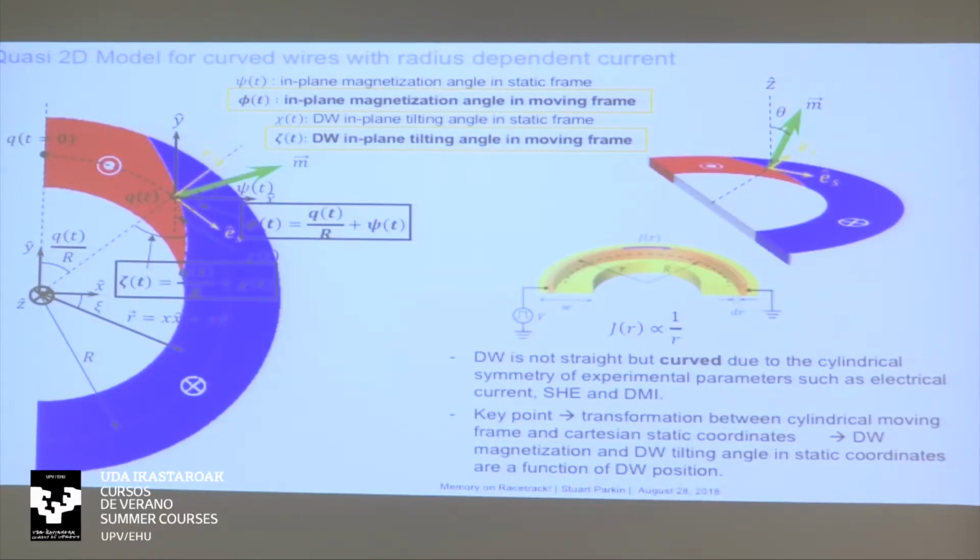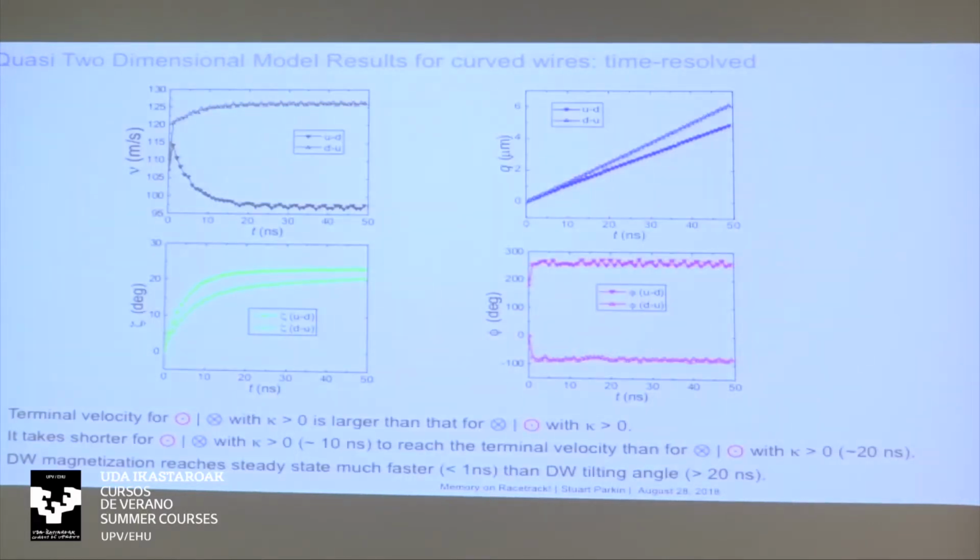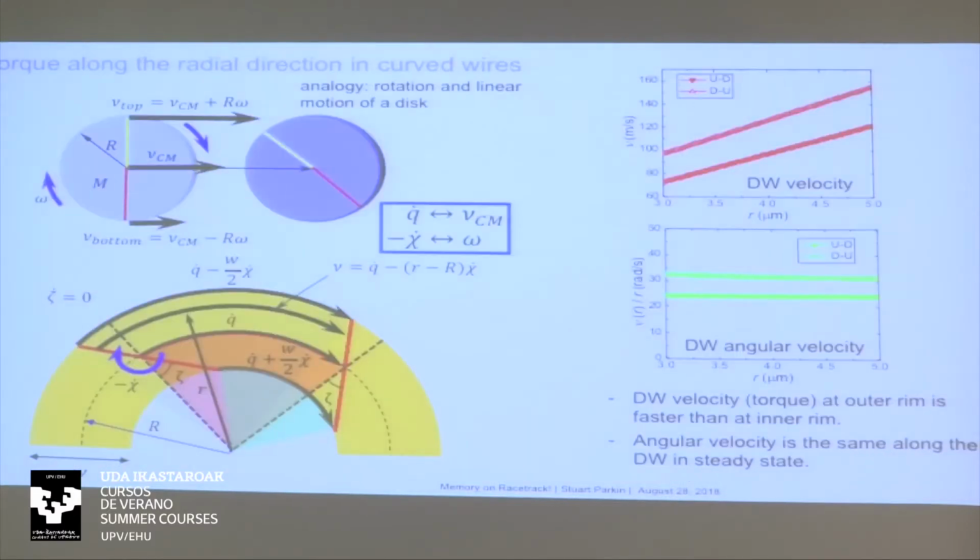We have to switch all that magnetization, and that turns out to take a very long time. So within the wall itself, the wall moments rotate in response to the spin Hall torques very rapidly, but this takes much longer, and we have two different timescales. The timescale for turning the straight wall into this complex shape that determines the constant motion of the domain wall takes tens of nanoseconds, whereas within the wall itself, it will evolve in a few hundred picoseconds. This is what happens, and we can model this, and now we understand what's going on.